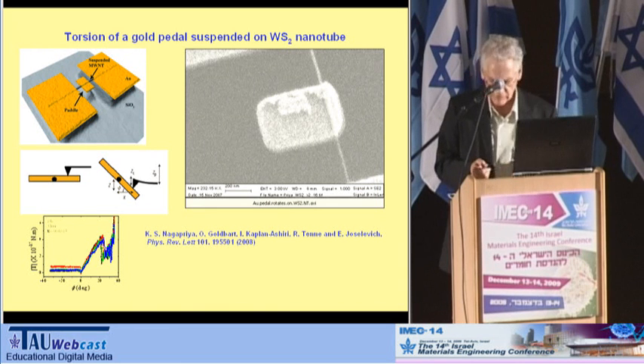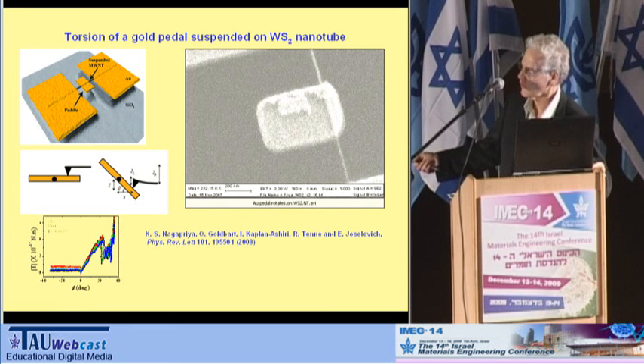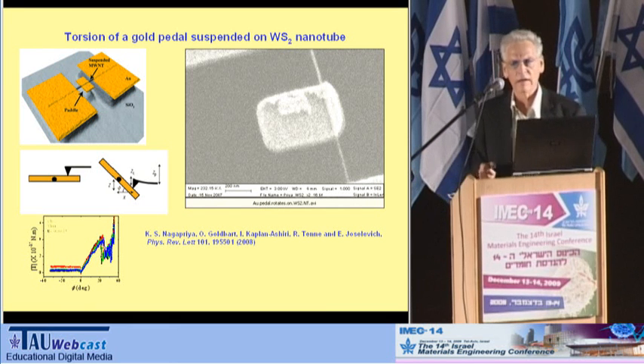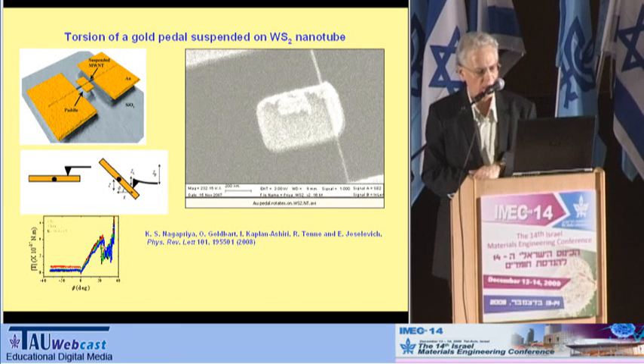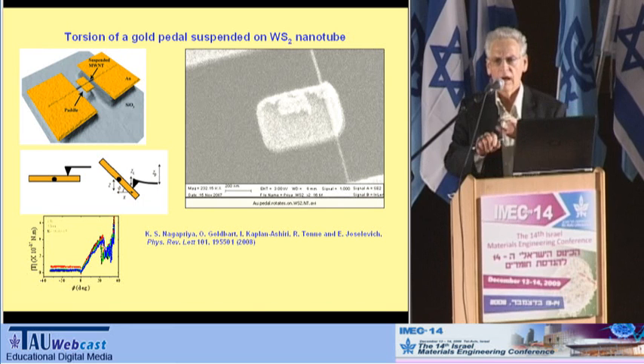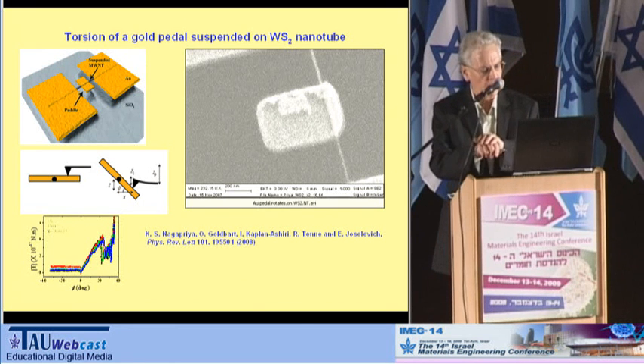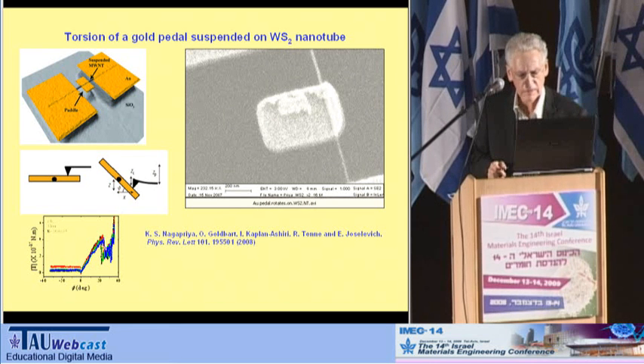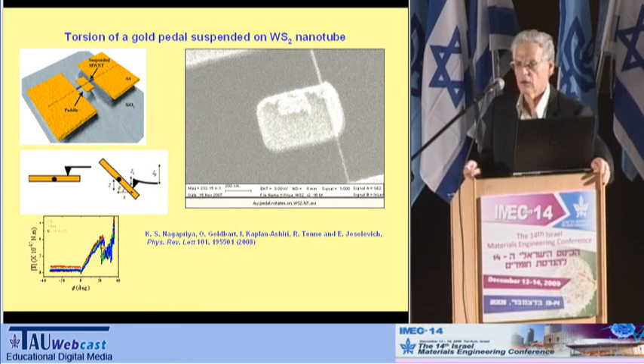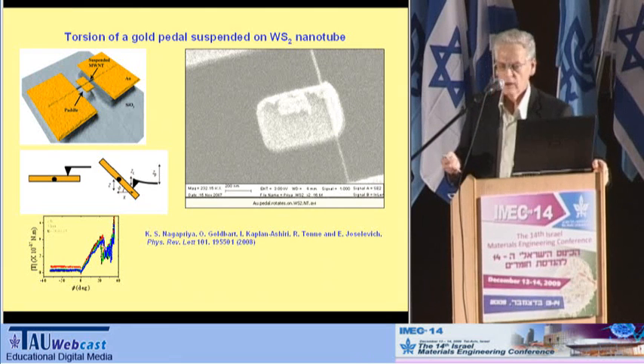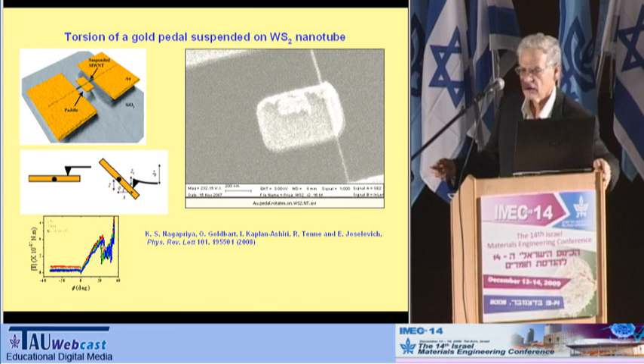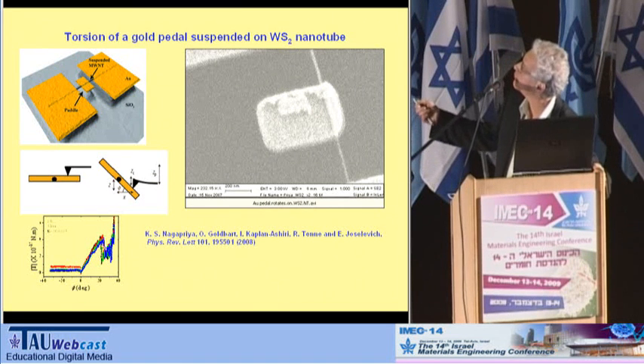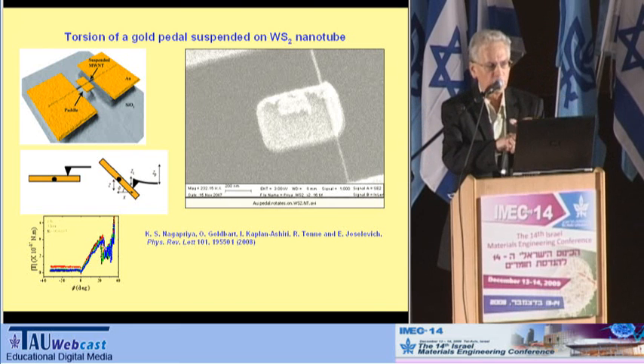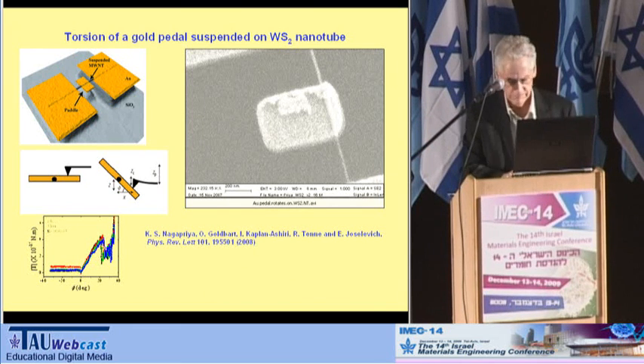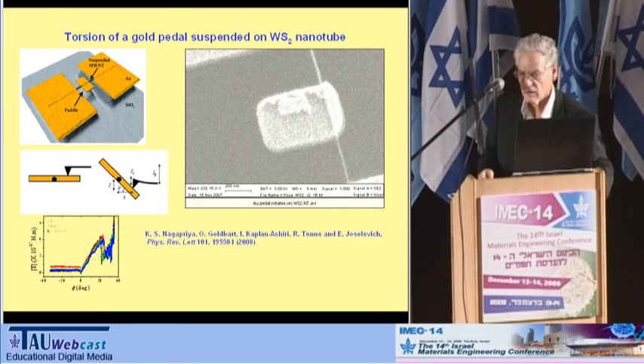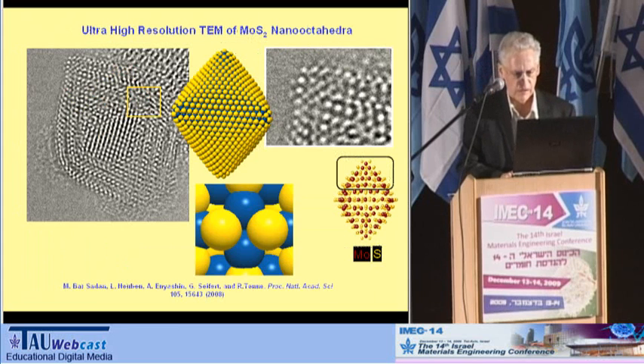They are very elastic, but at a certain point, they have some kind of a catastrophic event, and that actually is not an inelastic or a plastic deformation. It's just a shearing of the outermost layer of the nanotube on the inner layers of the nanotube. That has clearly been demonstrated by a combined theoretical and experimental study. So when you go to a very high angle, the outermost layer is detached from the inner layers and starts to rotate freely. And you see afterwards a series of such events, also of shearing of the outermost layer.